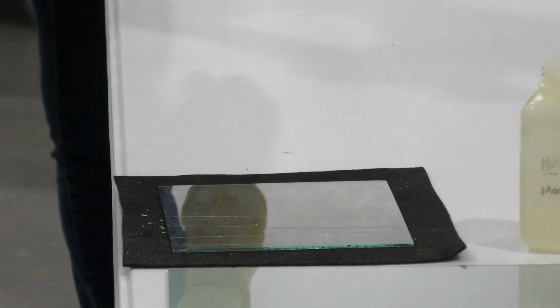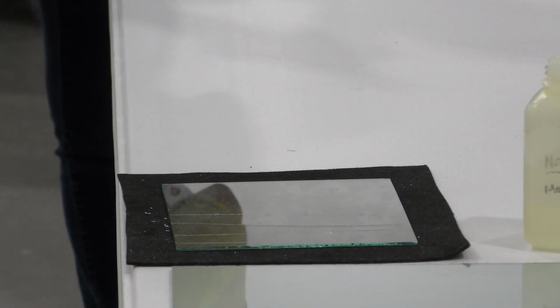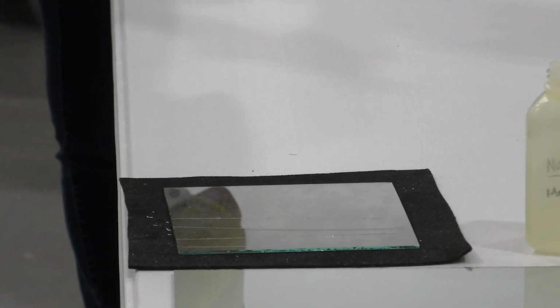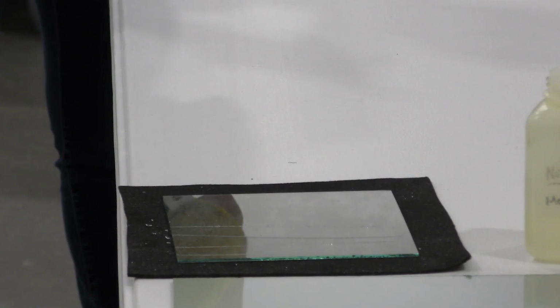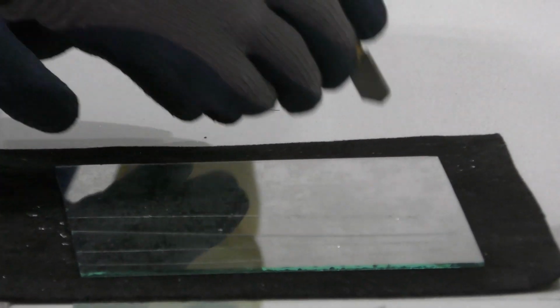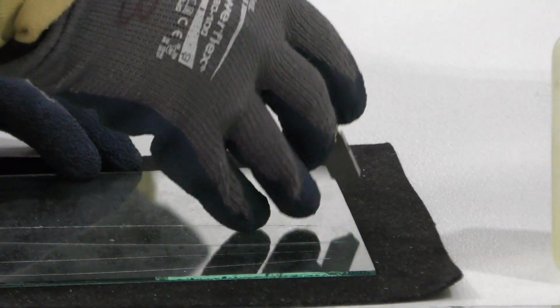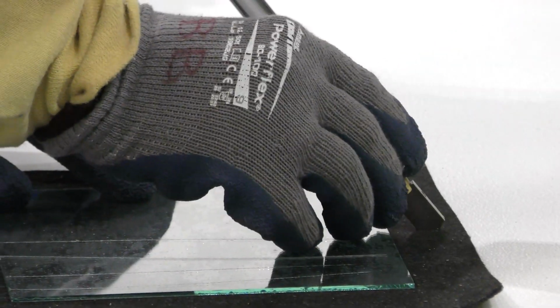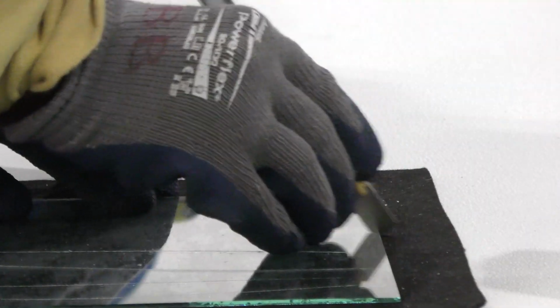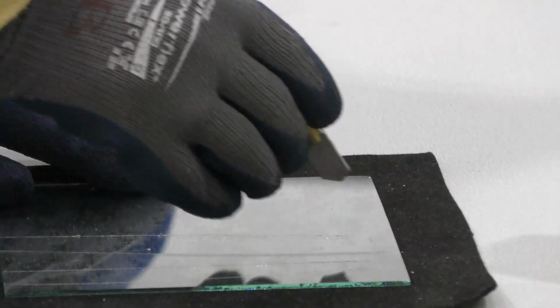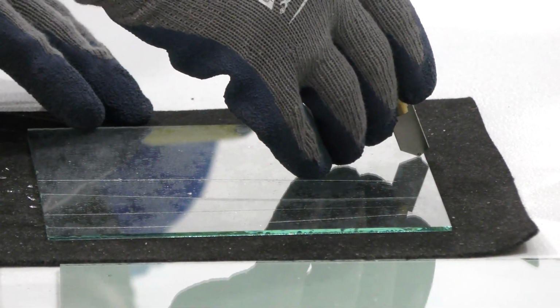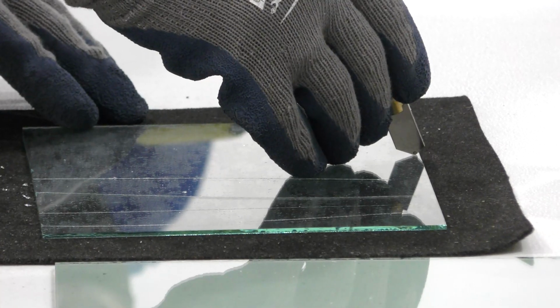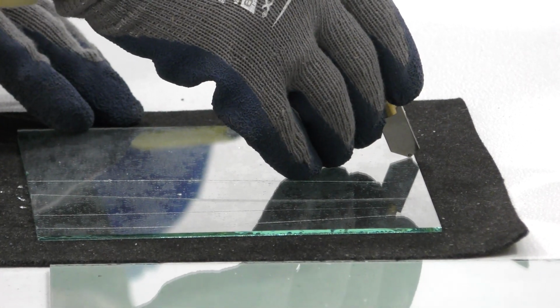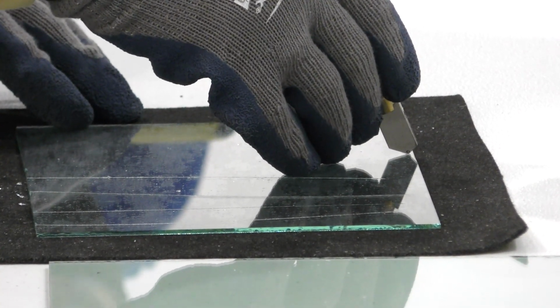So if I tilt the tool, what have I done to the angle? I've made it sharp and blunt on the same one. So you want to make sure that you're completely vertical. It's very important. You want to start close. You never want to start off the glass and on. You just made a defect. You want to start very close to the edge of the glass. Go with consistent speed and pressure or force down.